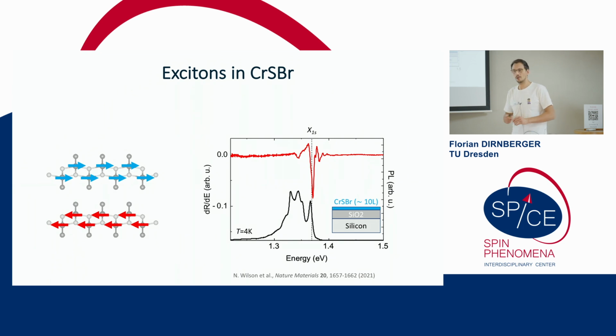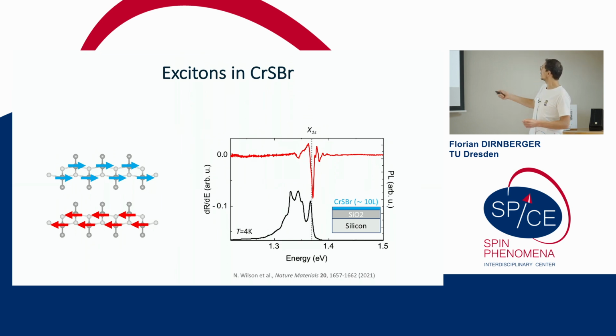So chromium sulfide bromide, we've heard a lot about it. Just to remind you, when I say excitons in this material, I really mean these spectral features in the near infrared part of the spectrum that can be very easily seen, particularly at low temperatures. So you can see here this sharp, strong resonance of the exciton in the reflectance contrast or the derivative of that signal. This means light is absorbed quite a lot, which means the exciton oscillator strength is large. And that's good, that's what we want. And then you can also see this emission spectrum, and there's this one peak that matches quite well with this resonance, and then there's a couple of other peaks that are not too important for now.